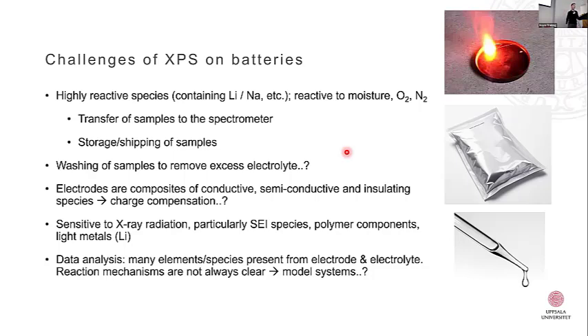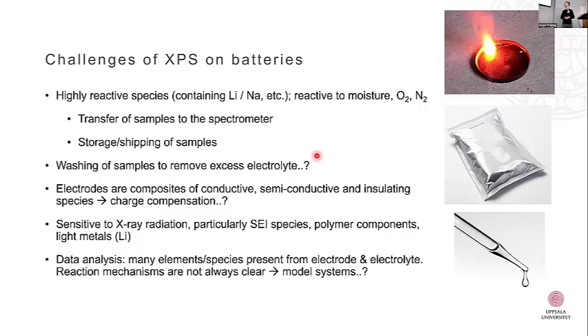The next point is washing of samples. Typically we want to remove some of the excess electrolyte from the surface of the sample; otherwise the salt will crystallize out on the surface and potentially block the signal of the SEI or the material we're trying to study. Whether or how to wash, and to what extent, is still an open discussion point in the community.